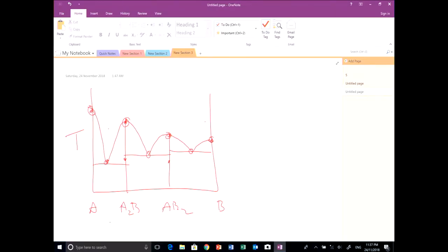What actually happens is what people used to do in the old days when the equipment was really primitive. They'd actually watch A and B diffuse into each other, and then they'd polish the microstructure, and they could actually pick out the locations of the different phases. And they could analyze the phase diagram from the microstructure.